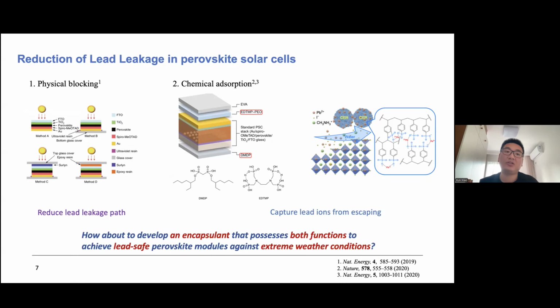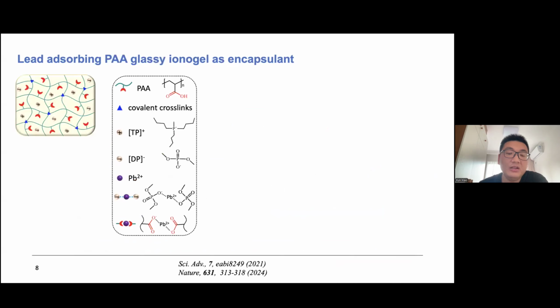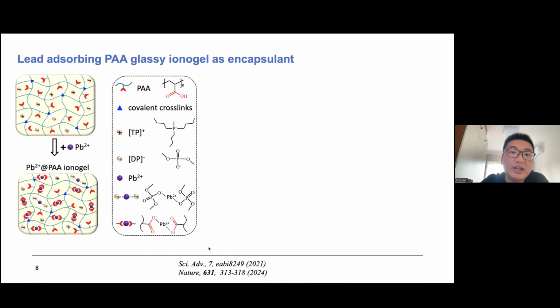That means we want the physical blocking and we want the chemical adsorption to get the lead-safe perovskite module against the extreme weather conditions. So this is a work that we have developed, the PAA glassy gel. We published how to improve the mechanical property in this Nature paper. And then we use this PAA glassy gel to modify the function of the polymer chain.